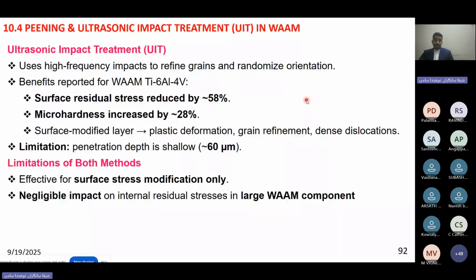Some authors proved that surface residual stress was reduced by ~58% after ultrasonic impact, and micro hardness increased by 28%. But there is a drawback. Both shot peening and ultrasonic impact cannot penetrate the entire thickness of the wall, only up to certain layers. For example, up to 60 or 50 micrometers only will there be impact. That's the thing.